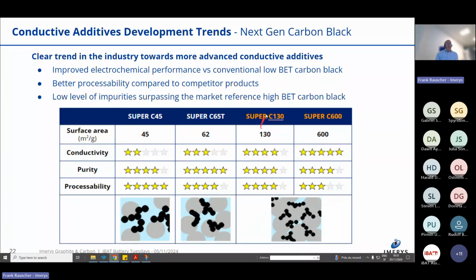Those are products you can buy from us today. And by the end of this year, we will launch what we call a Super C130 and a Super C600. The name indicates the specific surface area in square meter per gram. The higher you go in surface area, the better the conductivity is. So for instance, for a Super C600, you only need to add half of what you need to add for a Super C65T to get the same conductivity in the cathode. And of course, that is value to customers because they can add 0.5% more active material, which allows them to go to a higher energy density.